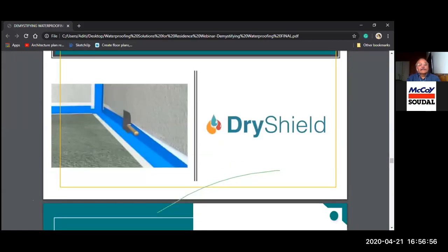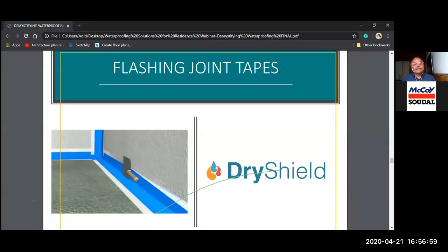Flashing joint tapes can be used, these are for bathroom areas. This is done only after the construction has been done, where there may be a problem for the joint, or even for new joints where there is no problem, and it's being done as a protective measure. So let's say a bathroom wall and floor joint or wall to wall joints, up to maybe 350 mm from floor level, the flashing tapes, joint tapes should be fixed.